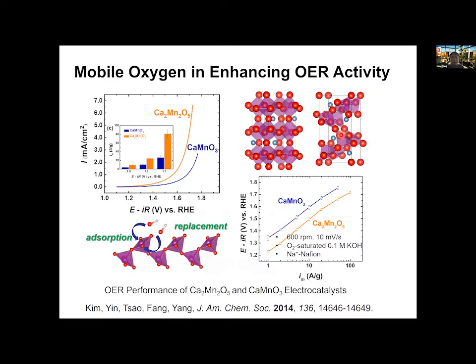A quick introduction: our first publication in this space is the so-called calcium manganese-based system, which shares some similarity with the brownmillerite type of structure. The key feature we hypothesized at that point is that if we have molecular-level or atomic-level oxygen vacancies, together with a proper electronic structure on the manganese side, that could potentially improve the reactivity, even though the major reaction center should still be on the oxygen. At that point, we speculated that oxygen mobility could cause the activity changes.